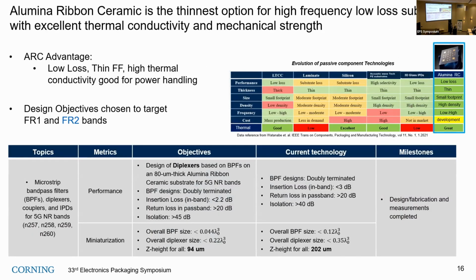So far I have shown the material properties. We have an excellent substrate, but we need to show how actual devices perform when fabricated on it. Here is our comparison of alumina ceramic with the incumbents, like LTCC or laminate or silicon or acoustic substrates and 3D glass IPDs. Alumina has most of the advantages, and especially it can beat everything in terms of thermal, and having very low loss is a big asset. So we built microstrip bandpass filters, diplexers, and IPDs for the 5G NR bands, especially the FR2 bands N257, 258, 259, and 260, which is maybe the 24.2 to 43.5 gigahertz range.